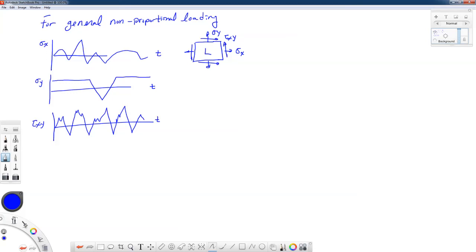So I have these histories here, and there's a whole lot of things that we have to think about now. If we want to do any kind of data reduction on these time histories, we have to be super careful now because we have all three of them. We don't want to miss a peak in one channel while we have maybe something constant going on in another channel. But the idea here is that if we were to take a look at a sequence of points in time for these different stresses, we can construct more circles as a function of time, and you can see this Mohr circle expanding and contracting depending on the value of the equivalent stress.